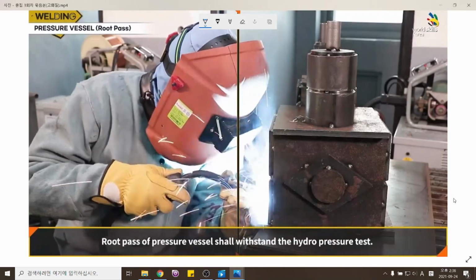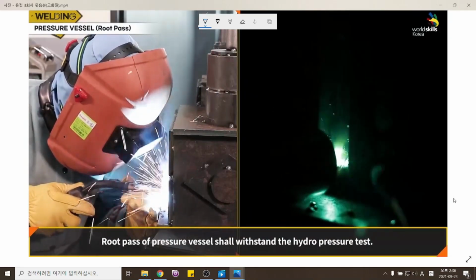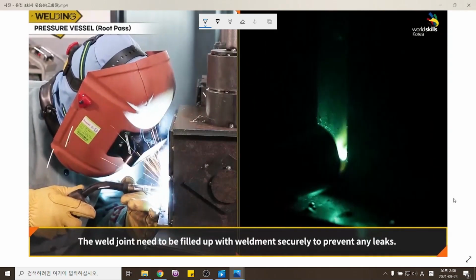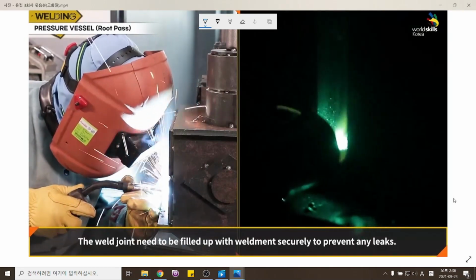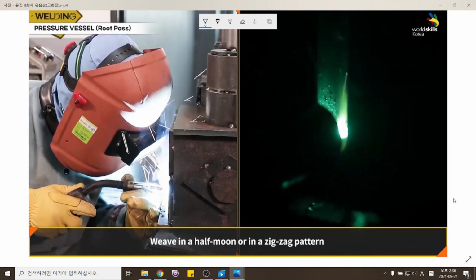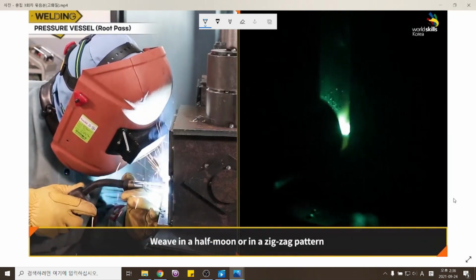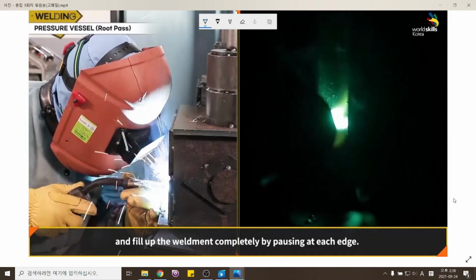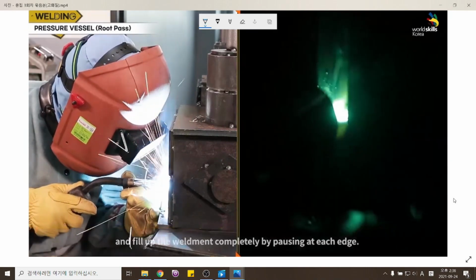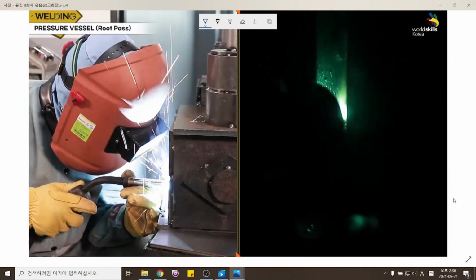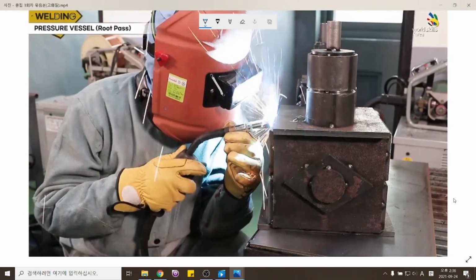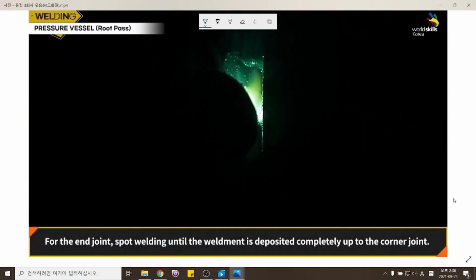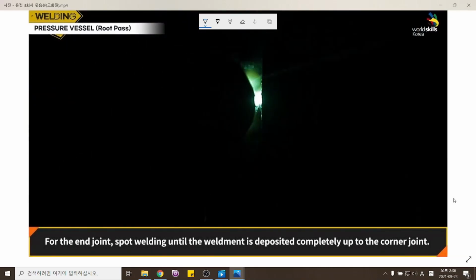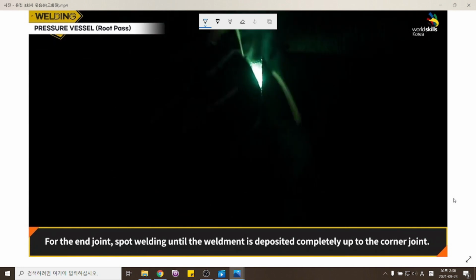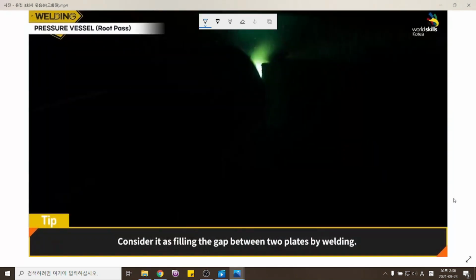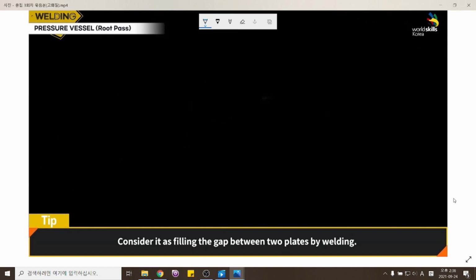Root pass of pressure vessel shall withstand the hydro pressure test. The weld joint need to be filled up with weldment securely to prevent any leaks. Weave in a semicircular or in a zigzag pattern and fill up the weldment completely by pausing at each edge. For the end joint, spot welding until the weldment is deposited completely up to the corner joint. Consider it as filling the gap between two plates by welding.